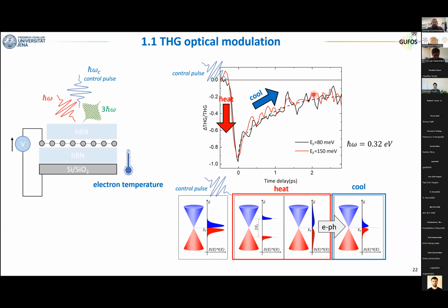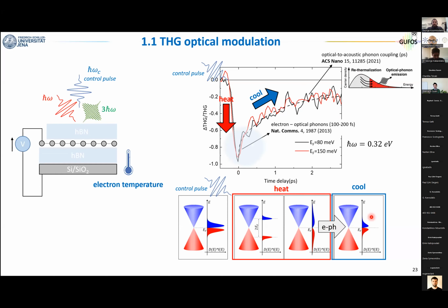Now, this recombination dynamics represents the sequence of events that I was discussing before. And if you zoom in, you will recognize that there are mainly two dynamics at play. The first one is very fast, it takes approximately 100 femtoseconds. And this is typically attributed to this process here, the electron-phonon scattering. So the electrons couple to the optical phonons of the material.